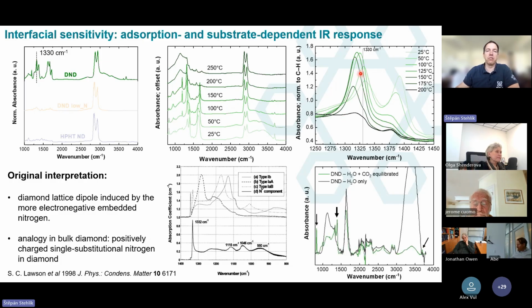The reason is the adsorbed CO2 from the air, which we confirmed by this experiment when we compared the ambient equilibrated sample, that's the green spectrum, with this Raman-like peak, and also with this little sharp peak, which is also coming from the CO2. And then when we rehydrated the sample but without CO2, we saw just the OH bonds, but not restoration of this peak, and also not this peak.